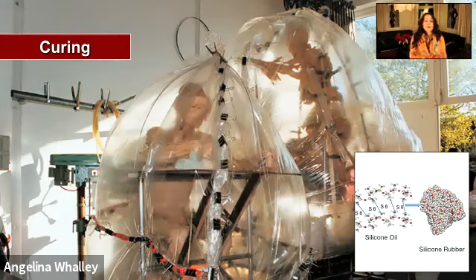The curing process depends a little bit on the kind of polymer that we use. If we use, for instance, epoxy resins, that would be cured by means of heat. Polyester copolymer would be cured by means of UVA light. But when we do silicone specimens, and these are the most specimens that we produce, we use a special gas. And that is actually a special invention Gunther did.